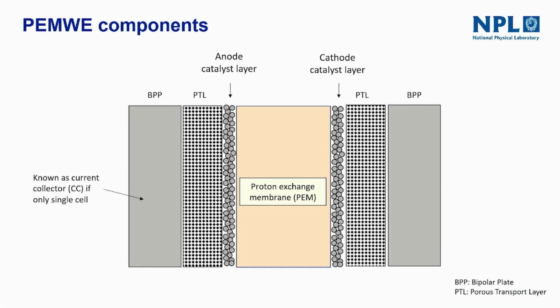This is a bit more detail about the structure, and we're very interested today in these 2 components, the bipolar plate and the porous transport layer. So all of the fancy electrochemistry happens at the electrodes, the anode catalyst layer and the cathode catalyst layer. So this is a very expensive material. This is iridium or ruthenium oxide, and the cathode is platinum-based, supported on carbon. But we're interested in these less sexy components because actually they make up a greater share of the volume, mass, and cost of the stack.